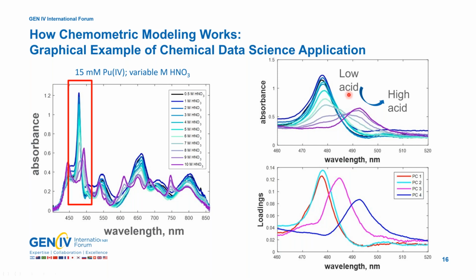However, in this region of the spectrum where we have a lot of plutonium-4 signal activity, we see that our model's working very, very hard to capture that down here. Now, what's a lot of fun is that if you really take a good look at these principal components that our model pulled out, and you go and read through some fun literature from the 1960s, what you see is that these fingerprints of these principal components overlay very nicely with fingerprints of the different plutonium species.